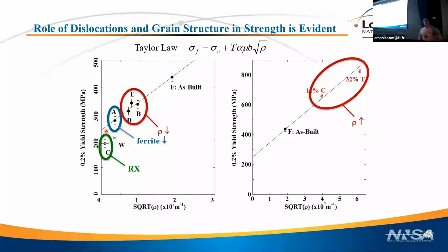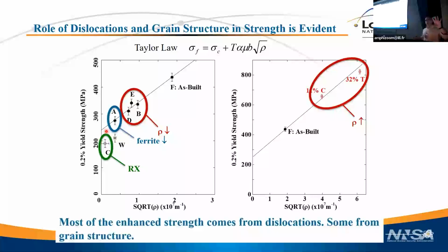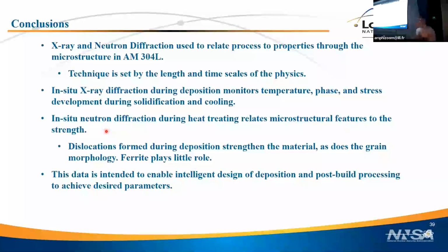So for those four things in the microstructure that I identified, the two that give the additively manufactured material extra strength are the dislocation density and the grain morphology. Forget that ferrite fraction word. Okay, at that point, I'm tired, I'm a little sweaty, and we're out of time. So let me wrap up.